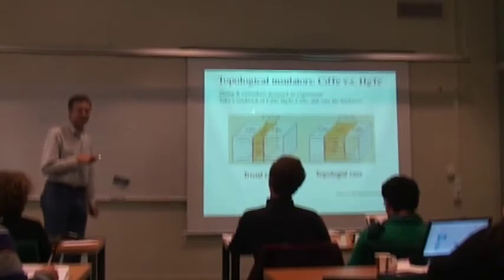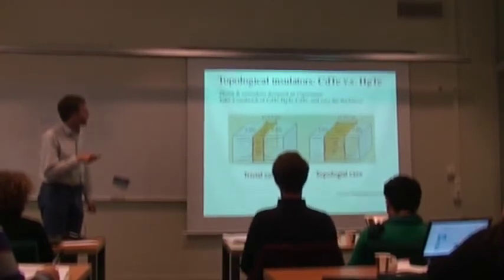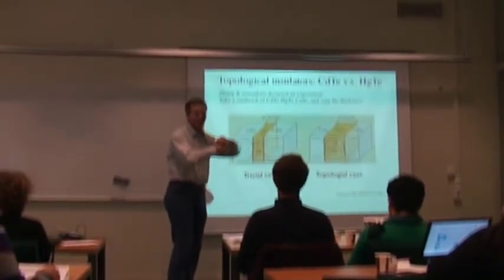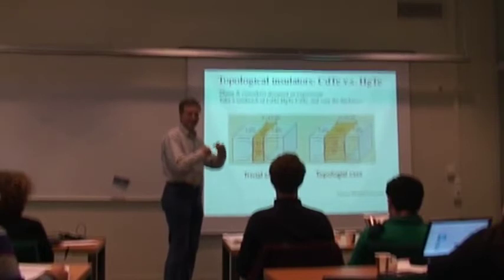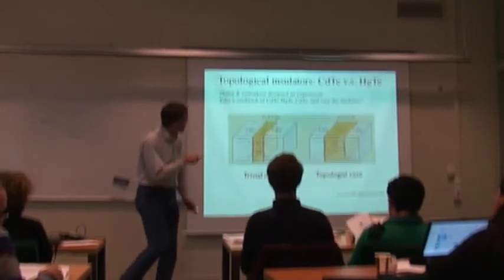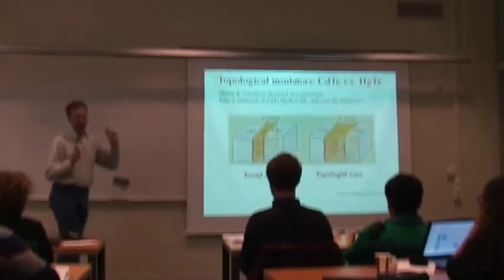So why do they use these materials? Well, these people know their semiconductor physics very well. First of all, to make these interfaces, you have to be able to stack these materials on top of each other in a very good way. It turns out that the distances between the atoms in cadmium telluride and mercury telluride match very well, so you can make clean interfaces. The reason they use mercury telluride is that it has the right properties to be used for topological things. In the end, that has to do with properties like spin orbit coupling and all that.